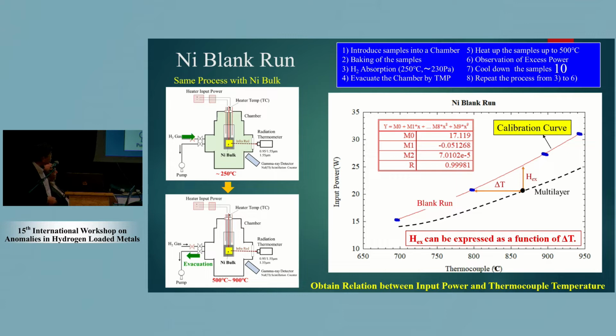And in the case of a multi-layer thin film, we get 860 degrees centigrade. So we can observe the delta T, the temperature difference between multi-layer and blank. So based on the model, excess heat can be expressed as a function of delta T. So we can estimate the excess heat by the delta T.